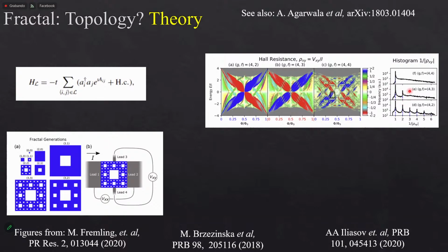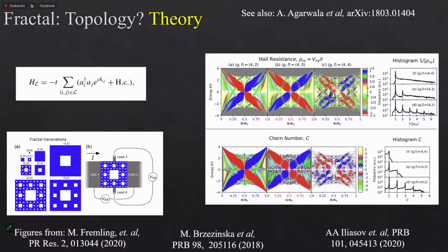But as you're making more and more holes in it, basically you're destroying this kind of topological phase. And the same thing occurs if you measure what's called the Chern number, so using this topological invariant in the bulk of the system. So long story short, basically they show that you can also have this phase, but usually the fact that you're making this fractal kind of destroys a bit the topology, although it changes its features qualitatively. But it was something interesting that they show that this can work.